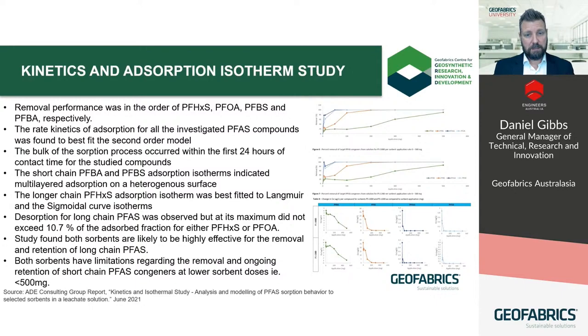So we selected a particular bituminous coal-based activated carbon, which had already been designed by the manufacturer to assist in the capture of PFAS molecules. And we recently carried out a kinetics and adsorption isotherm study through ADE to understand and really quantify the performance of the activated carbon in isolation of the bentonite component. We used a landfill leachate as the contact liquid because it had a range of potentially fouling co-contaminants, which are a very important consideration when looking at performance.